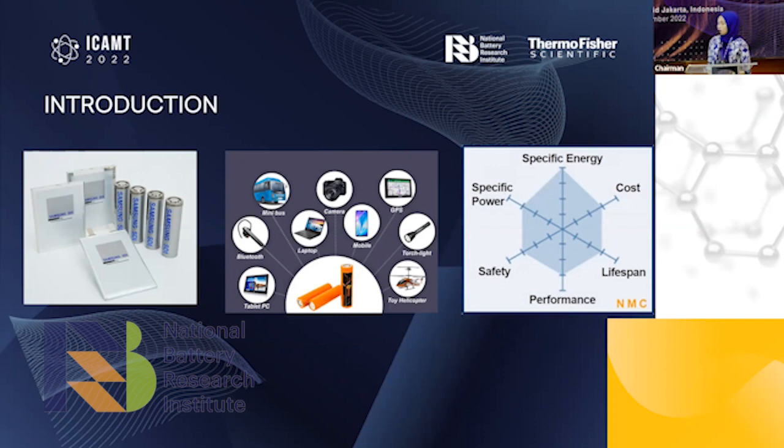The major performance enablers of batteries are advanced materials such as cathodes, which are crucial in defining the core structure, environmental impact, safety risk, and recyclability of the battery cell. Lithium nickel manganese cobalt oxide, or NMC, is one of the dominant battery materials because of its low price due to less cobalt usage, high abundance, structural stability, high capacity due to high nickel content, stability from the manganese, and long life cycle. Compared to LiCoO2 cathodes, NMC-based cathodes also combine the advantages of transition metals, with nickel offering high specific capacity, and cobalt and manganese providing layered structure and improved structural integrity.